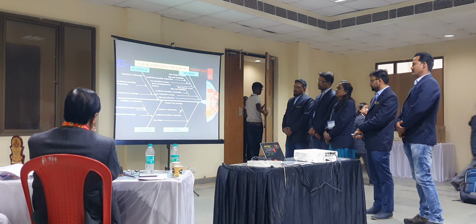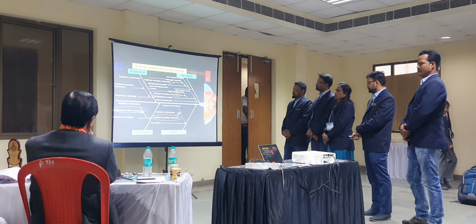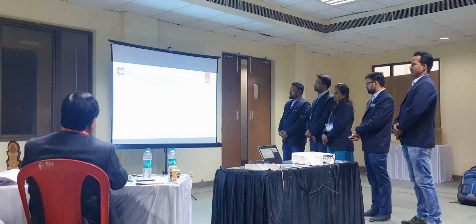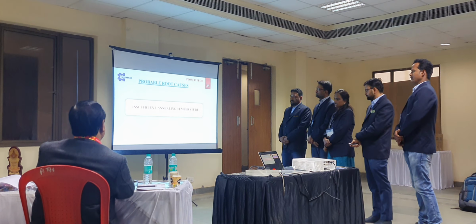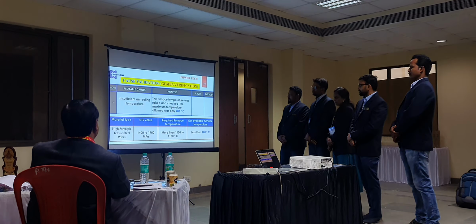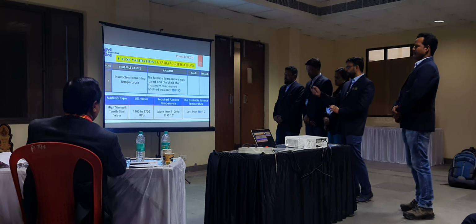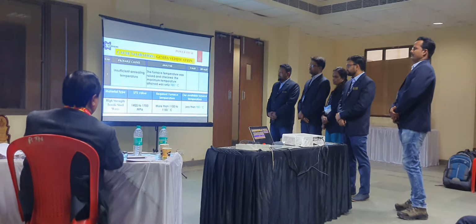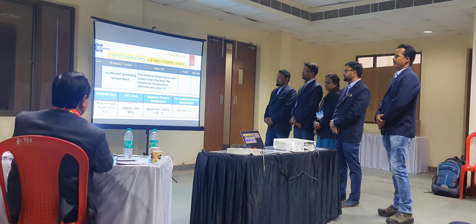After analyzing all these possible causes, we concluded the probable cause is insufficient annealing temperature. So, the probable root cause is insufficient annealing temperature. Here we did the Gemba verification for cause validation, and for the probable cause, we analyzed that the furnace temperature was only going up to 980 degrees Celsius.